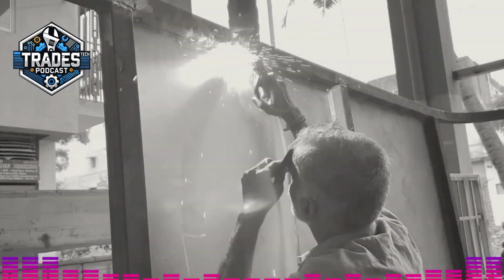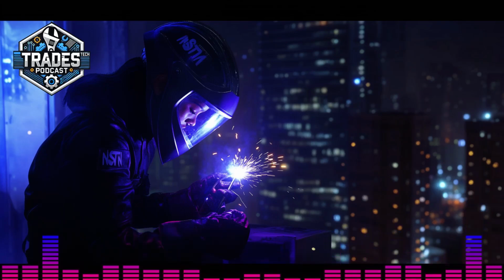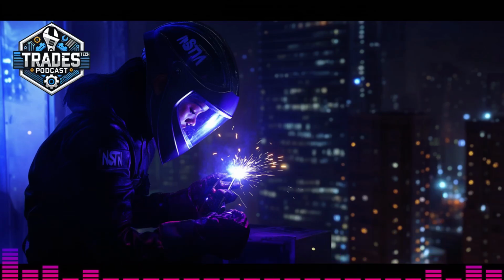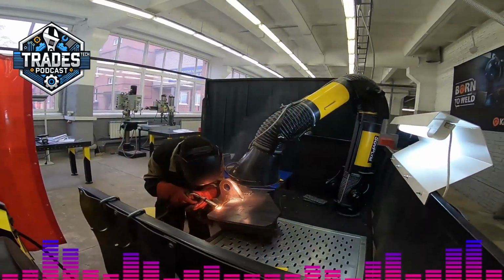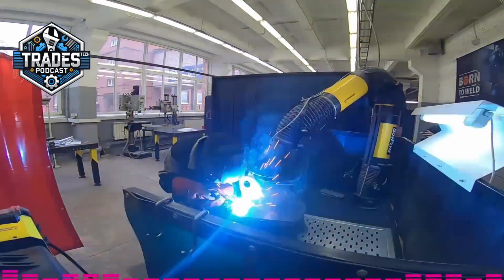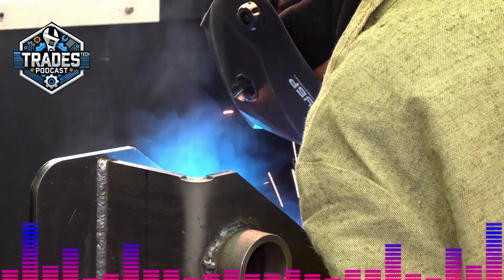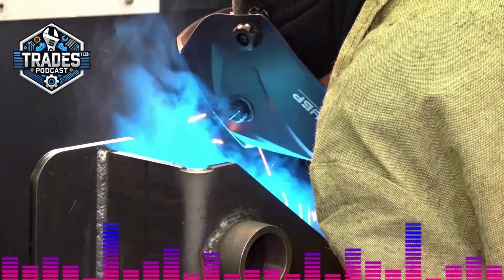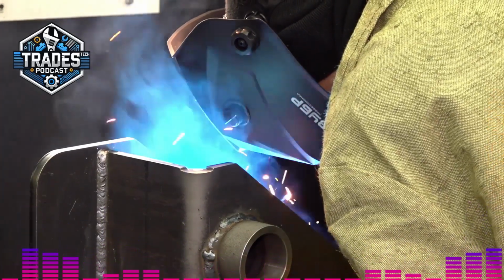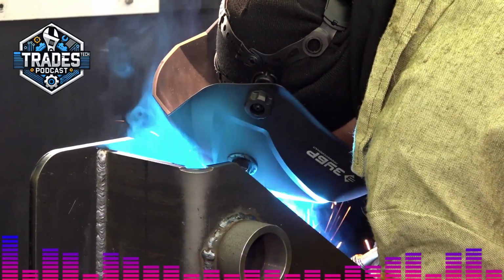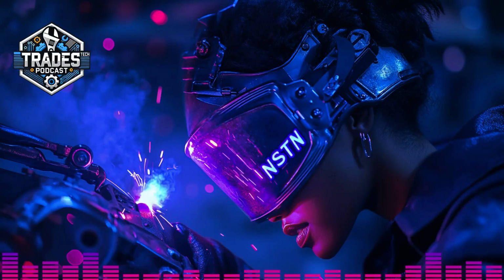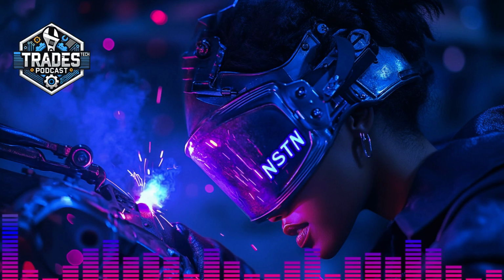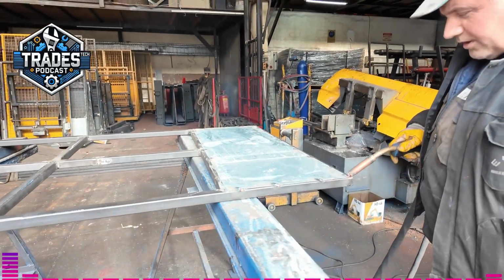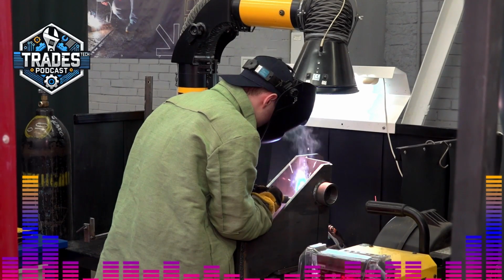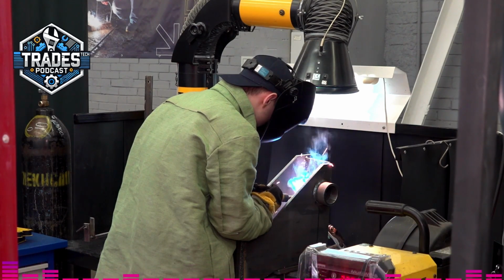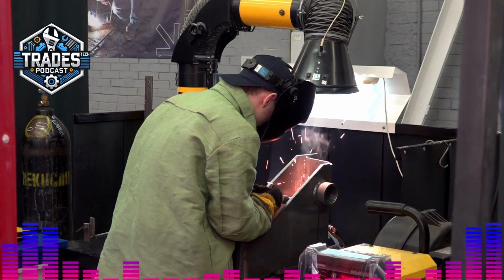Data from welding consumable manufacturers and industry testing consistently shows that self-shielded FCAW can tolerate wind speeds significantly higher than processes relying solely on external gas shielding. While recommended limits vary by wire and application, it's generally accepted that FCAW-S can handle drafts up to 25 miles per hour or even higher before significant issues arise, whereas MIG welding is often limited to wind speeds below 5 to 8 miles per hour without wind breaks. That's a massive difference when you're working outdoors. 25 miles an hour is a pretty stiff breeze. That capability alone makes it indispensable for many jobs.